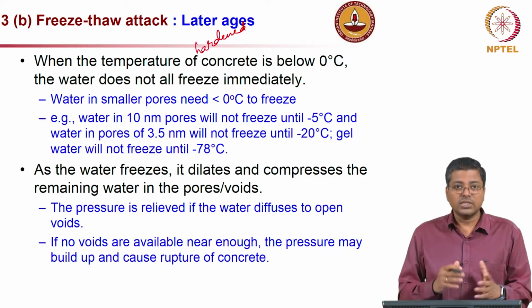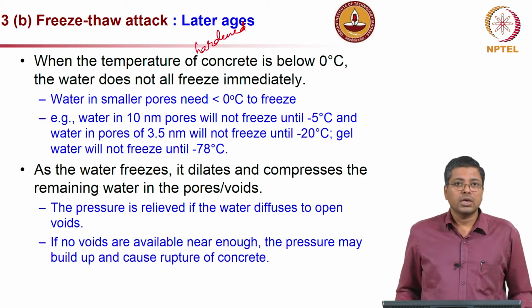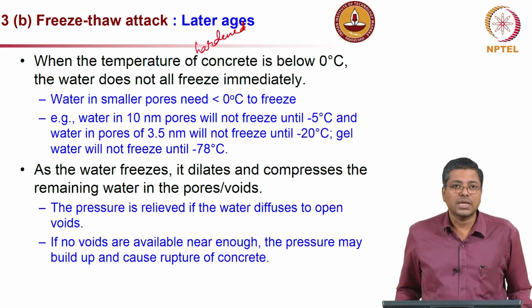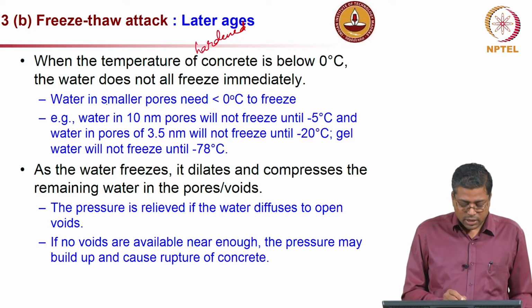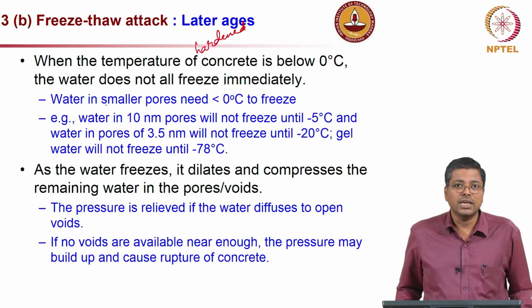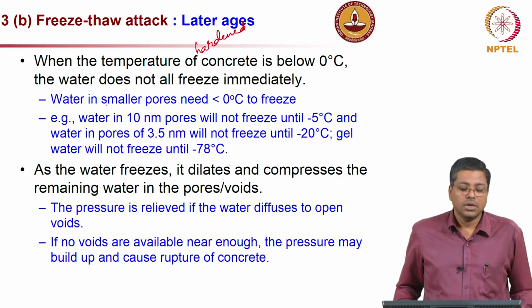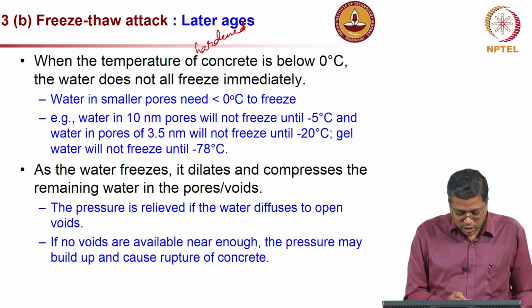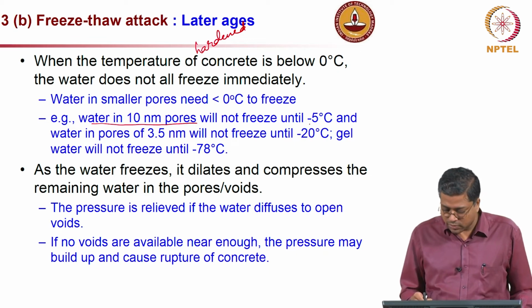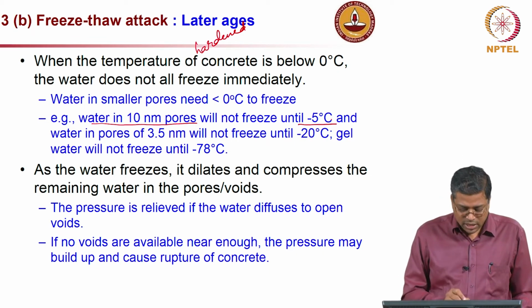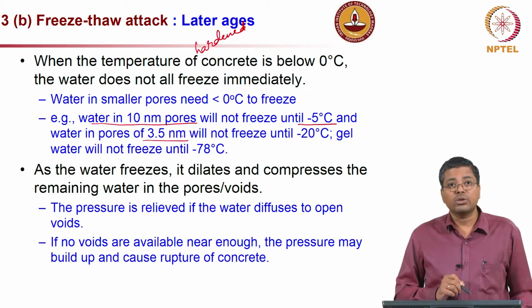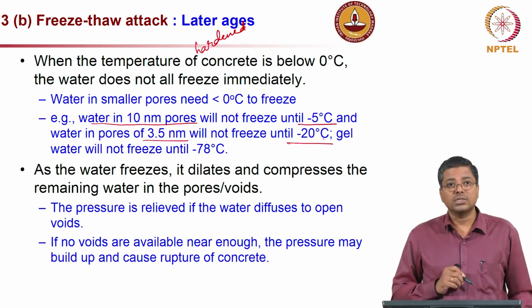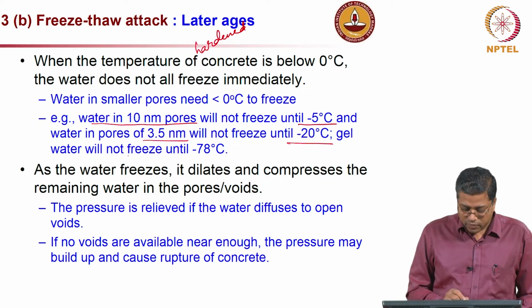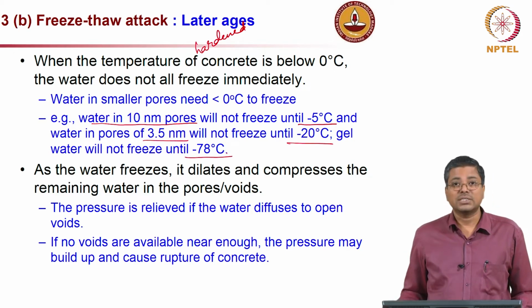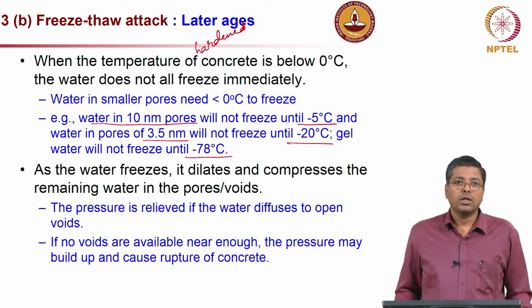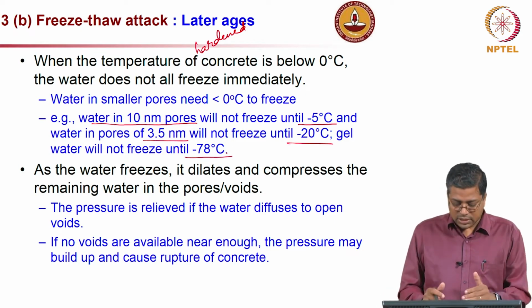So, the freezing point also depends on the size of the pores. Okay. So, water in the smaller pores needs less than 0 degree temperature to freeze. For example, if you are talking about water in 10 nanometer pores, it will not freeze until -5 degrees Celsius. If you are talking about 3.5 nanometer pores, it will not freeze until -20 degrees Celsius, and if it is gel water, it will not freeze until -78, that is much smaller pores. So, you can see this.